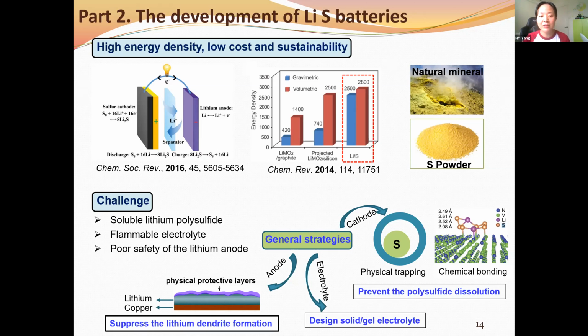The first one is the soluble lithium polysulfide. Polysulfide is generated and combined with lithium to form lithium polysulfide, which is soluble. When you use lithium metal as the anode and sulfur as the cathode, and you charge and discharge, the lithium polysulfide generated dissolves in the electrolyte. In other words, when you charge and discharge your battery, the electrode gets smaller and smaller, and that is the scenario for the current lithium sulfur battery system.